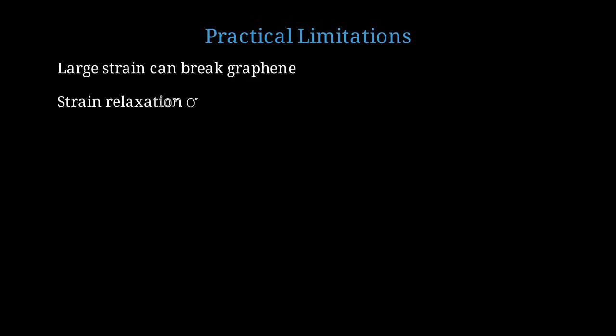Of course, there are practical challenges. Let's be honest about the limitations. First, graphene is strong, but not indestructible. Strains above about 25% typically cause rupture. So there's a practical limit to how strong your pseudomagnetic fields can be. Second, strain can relax over time, especially at room temperature. The configuration you create might not be stable indefinitely. Third, real samples have disorder and defects. These can scatter electrons and wash out the clean Landau-level structure you'd expect from theory.